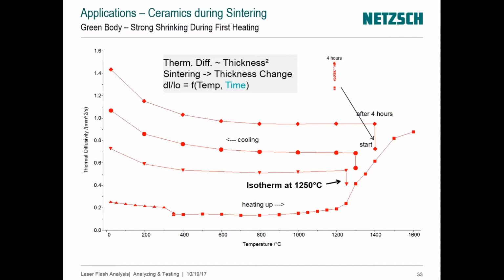And you see the diffusivity obtained. Obviously, this diffusivity is not as we would expect. In the next case, we do the initial isotherm at a slightly higher temperature, and we see that that would be the dots, and you see that as we keep measuring on the cooling side, the diffusivity increases much higher than what was obtained before at the 1250 degrees C isotherm.